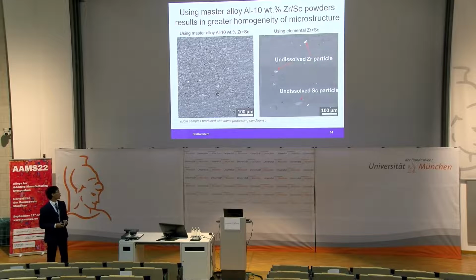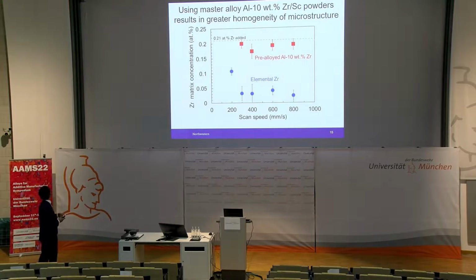Both these samples that I show here are produced with the same processing conditions. And what you can see from the micrograph on the left is that this microstructure is considerably more homogeneous than what we saw in the beginning. It's not perfect. You can see some of these white regions, which are pockets of concentrated zirconium, but there aren't any of those pure zirconium, pure scandium particles. We can also measure the concentration of zirconium dissolved by EDS, and what we see is that concentration of zirconium dissolved by using these pre-alloyed 10% zirconium powders is higher than when we use these elemental powders. And by the way, I focus on zirconium here, but all these observations also extend to scandium.